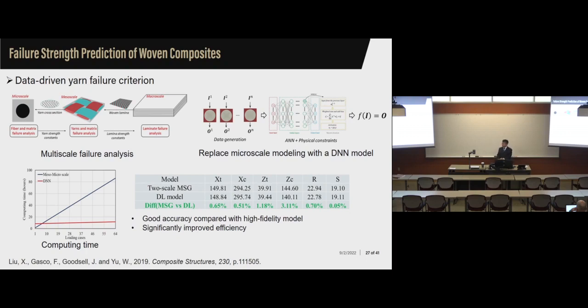So what we want to do is to numerically figure out the failure criteria or failure envelope for the yarn based on the micro level simulation. That's what we came up with. Because we used a very sophisticated machine learning model, a deep learning model, you'll find that comparing to the two-scale or physics-based simulation, we have a very small difference, less than 1% or around 1% for all the strength variables for the yarn.